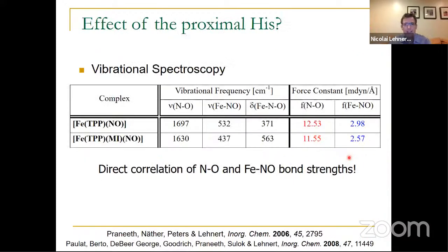we can skip this one here. We can bring it all back together into this slide here. This is the comparison now for this particular model complex, right? So this is the 5-coordinate complex, and here are the vibrational data with the NO stretch at 1697, the Fe-NO stretch at 532, and the bending mode at 371. And these are the force constants that you calculate from the simulation. And here's the 6-coordinate complex. So we had to work very, very hard, as I showed you, and use nuclear resonance vibrational spectroscopy. And we even had to do single crystals, just so we can make this assignment here. Right? The Fe-NO stretch at 437, the bending mode at 563.